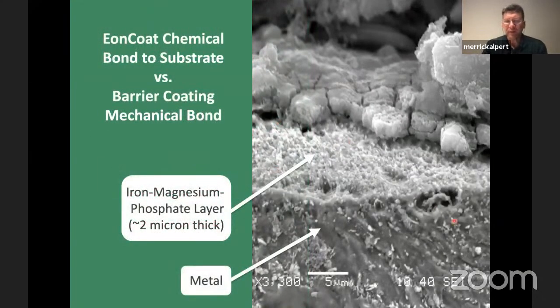This is a different scanning electron microscope photograph. This is in response to people saying, what does it look like at the passivation layer? What does it actually look like right on the surface of the steel that you've chemically altered to prevent oxygen and moisture from touching it? Again, you can see the steel at the bottom. You see up at the top the ceramic, and then through a series of actions, chemical and mechanical, we've actually torn away the ceramic. It took some doing, some time for us to figure out how to do it, but we tore it away. And then look what's revealed, the iron magnesium phosphate layer. That looks like white snow. That is the passivation layer that prevents oxygen and moisture from touching the steel.